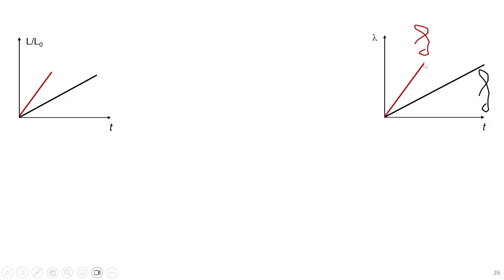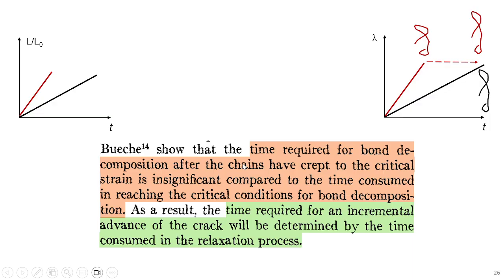So the idea I'm putting into his mouth is, if you stretch, the black is the continuous stretching. So until some point it stretches and breaks. If you all of a sudden stretch to the same level, his idea is the chain hasn't reached the critical strength. So it will take time to elongate, and you wait until it elongates. Because most time is consumed to elongate, to reach the molecular strength, rather than to wait for the bond to break. So my view is exactly the opposite. This is written in the paper. I paraphrase it. Basically it says, the system takes most of the time trying to get molecularly stretched rather than taking time at that stretching to break. And I have evidence to prove exactly the opposite.